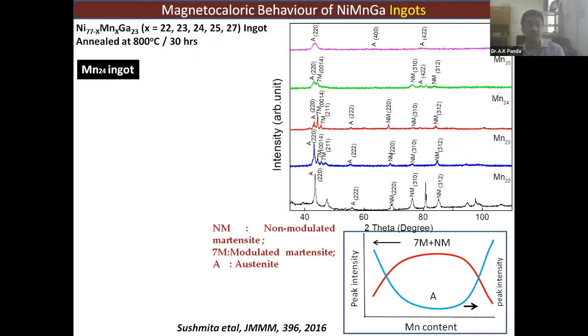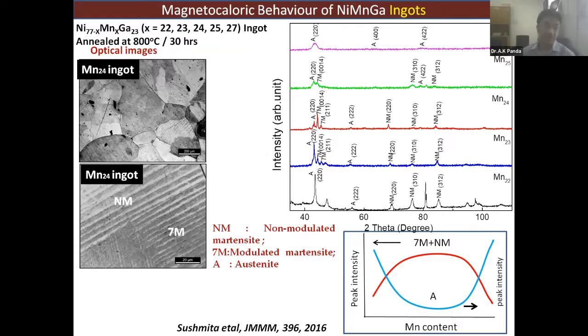This is typically your nickel manganese gallium with a lot of manganese variations. These are optical micrographs, sorry, of a typical alloy having 24 atom percent manganese. You find that the ingot, the top one, shows a granular structure, and when you magnify it, you find a combination of the non-modulated and the modulated martensites. You can even identify this using your X-ray diffraction.